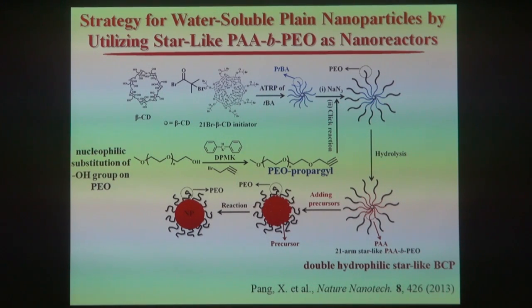To make this double hydrophilic star-like copolymer, we combined one-step atom transfer radical polymerization with click reaction. First of all, we made this multi-arm star-like poly(tert-butyl acrylate), PTBA, then converted the terminal bromine group into azide functionality by reacting with sodium azide. On the other hand, we prepared triple bond terminated PEO, polyethylene oxide, by nucleophilic substitution of the hydroxyl group with ethynyl magnesium bromide. Finally, the click reaction between azide-terminated star-like PTBA and the PEO propargyl yielded this multi-arm star-like PTBA-block-PEO. Again, we hydrolyzed the inner hydrophobic PTBA block into hydrophilic PAA, yielding this double hydrophilic star-like copolymer.